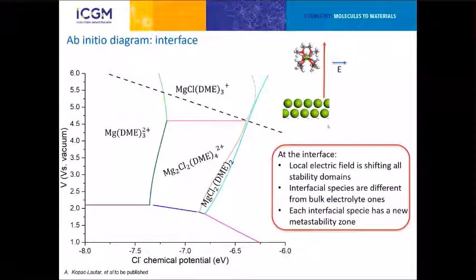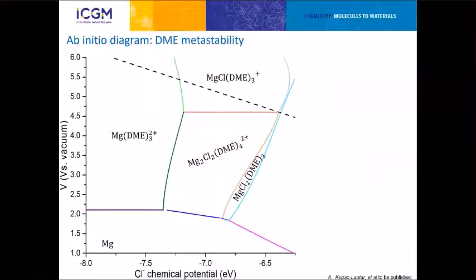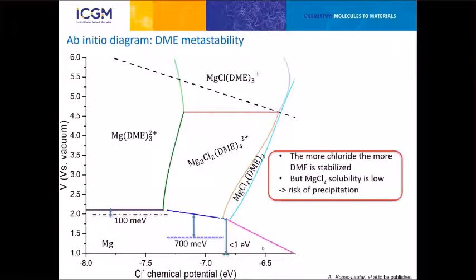And then once we have reached this, we can look at the stability of the species. Of course, with pure magnesium, we have observed a very low metastability of the DME. It starts to be reduced quite close to the limit of reduction of magnesium 2. But if we use some chloride compounds, the metastability range is strongly increased. And the more we add, the more it is increased. So chloride is certainly a very good thing to improve the electrolyte stability by, in fact, decreasing the electrophilicity of magnesium. But of course, if you add too much chloride, you are going to precipitate MgCl2 and you are going